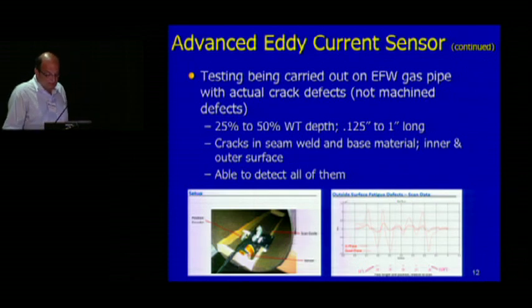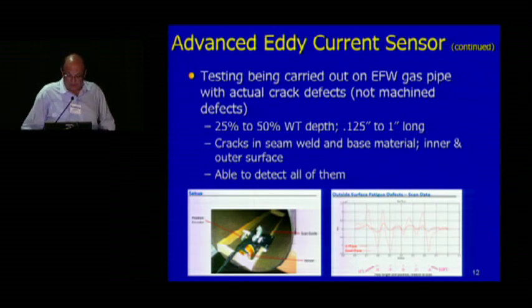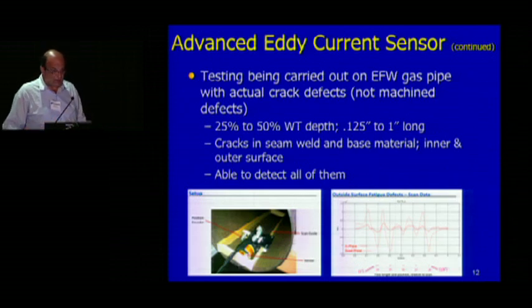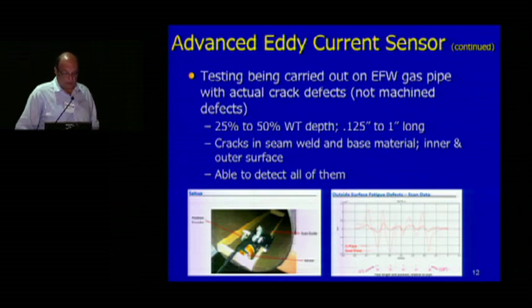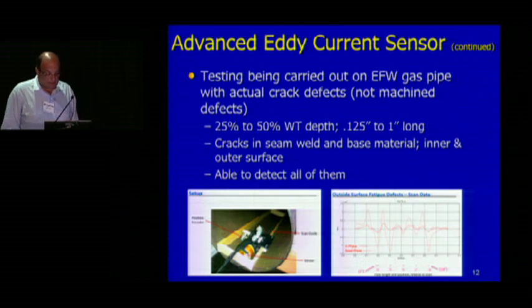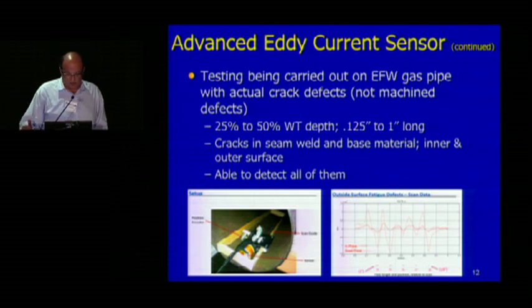So we actually have a gas pipe with an EFW weld on it, and we have actual crack defects on them. We were glad to find a company that is actually putting cracks on the pipeline rather than machined defects. So these are actual cracks. It's a proprietary process that they have. And we have cracks that are invisible to the eye. They're 25 to 50% wall thickness depth, and they have a length from an eighth to 1 inch. We put those cracks both on the seam weld and on the base material, both on the inner and outer surface of the pipe.